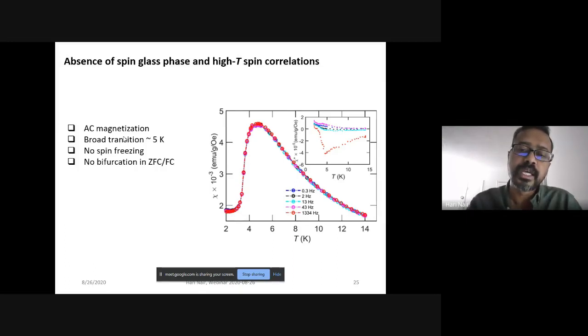We do that because if there was such a dependence, then that would indicate that the ground state is what is known as a spin glass state. It would then indicate that the ground state would have long time spin relaxations, and you can then use certain types of power laws to explain the whole phenomenon of frequency dependence.